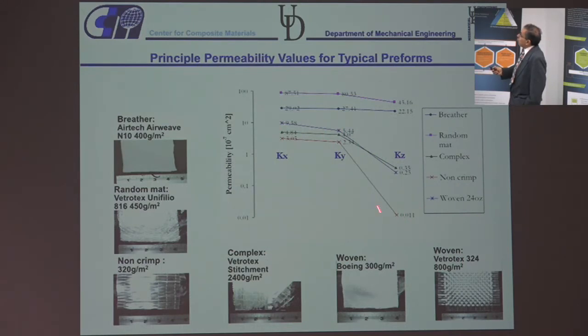What I want you to note is that in the Z direction, the permeability can be 2 orders of magnitude less than in the X and Y direction. So even if you're sending the flow really fast in the top plane, it is infusing in the lower planes much more slowly.